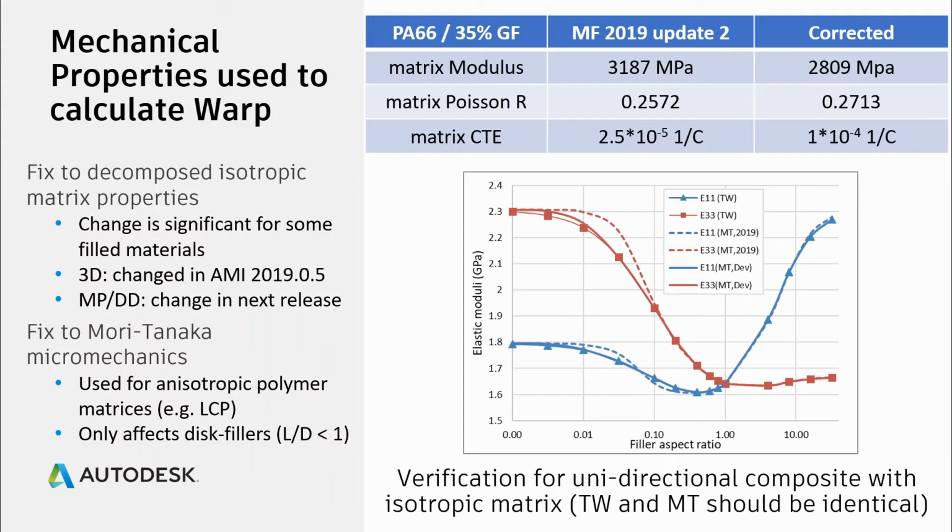And we see that the comparison between the Tandon-Weng and the Mori-Tanaka model deviated in 2019 at aspect ratios less than 1. However, with the new improvement, there's better agreement, with the Mori-Tanaka model now agreeing with the Tandon-Weng model.